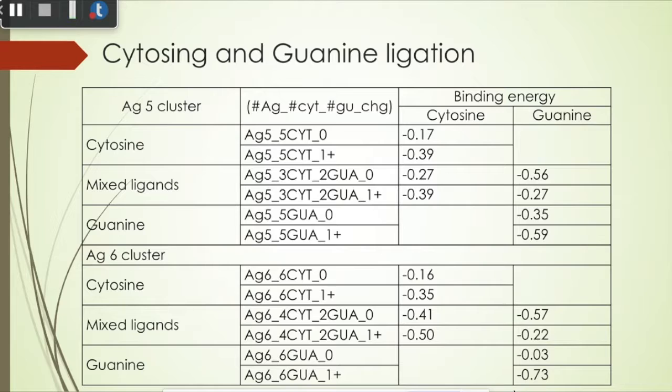So from that, we thought that guanine follows the same trend if we look at only guanine and only cytosine, but when they mix, it can follow the opposite trend. One experimental work also shows that if we introduce a guanine-rich DNA in the cytosine-rich DNA, it can increase the photoluminescence by 500 times. So maybe it's important to know how to change the photophysical properties by using this.